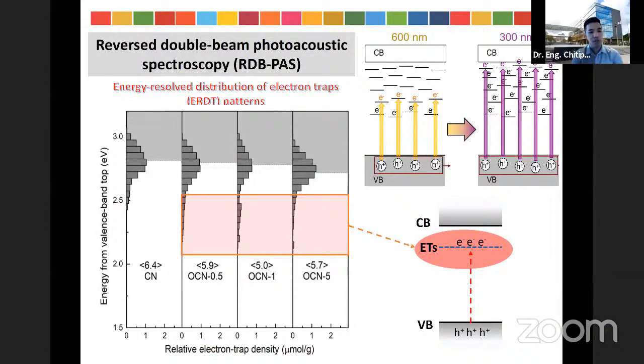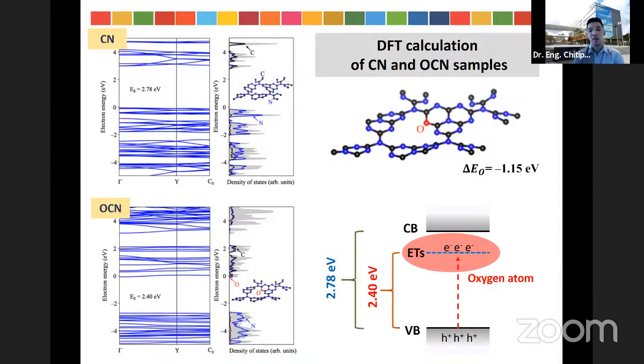And moreover, we also utilize the valence band XPS technique to confirm the generation of a new electronic state after doping by oxygen. And it's clear that the oxygen-doped sample shows a new electronic state around 2.2 or 2.3, which was lower than the conduction band bottom of the graphite carbon nitride. So the generation of the new trap state can avoid the recombination of the electron-hole pair. Also, DFT calculations of the pristine graphite carbon nitride, or CN, and the oxygen-doped graphite carbon nitride, or OCN, were performed to know the new electronic level compared with the ERDT pattern.